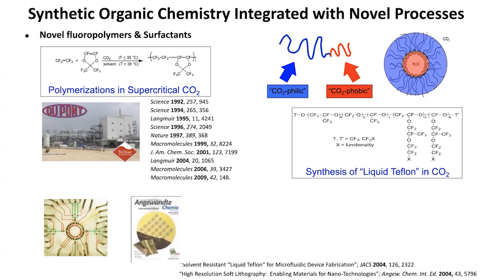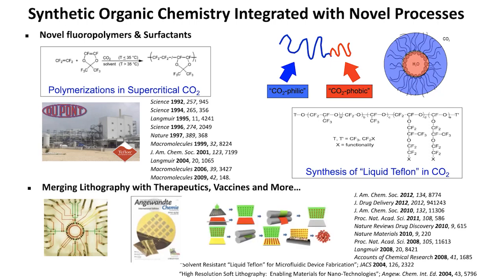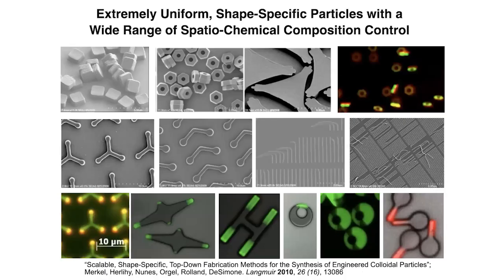And then we were watching what George Whitesides was doing in imprint lithography and the swelling of organics and silicones there. And we started using these liquid fluoropolymers as an alternative to silicones, just like we did in microfluidics. And then we realized that we could actually start molding particles in these imprint lithography molds. And we developed the technology we refer to as PRINT, particle replication in non-wetting templates.